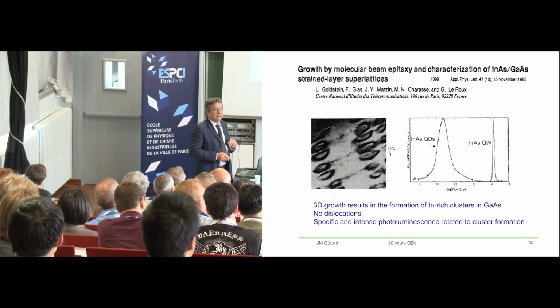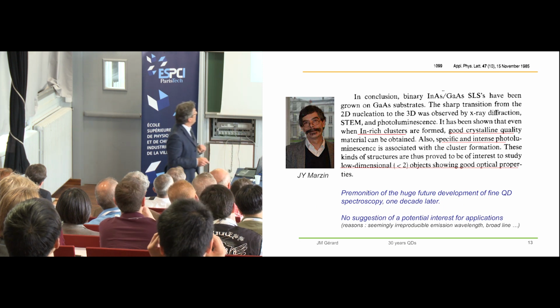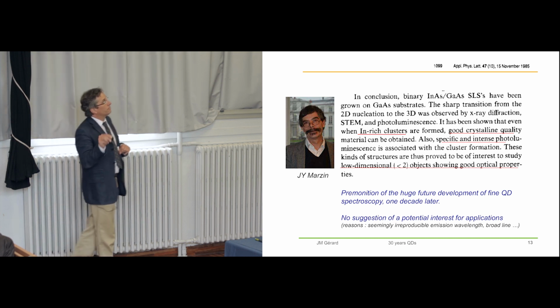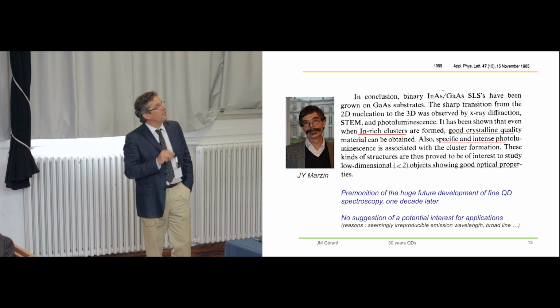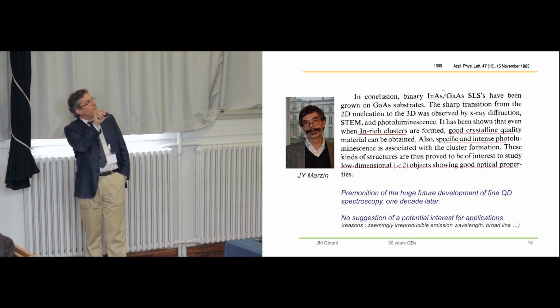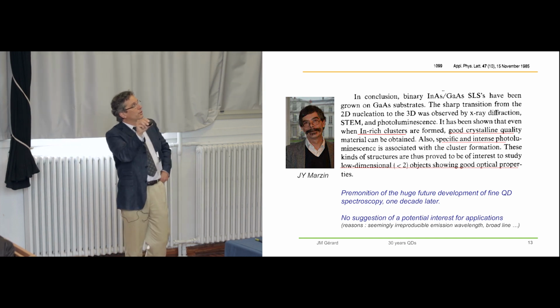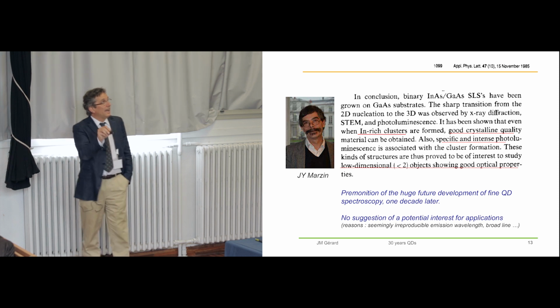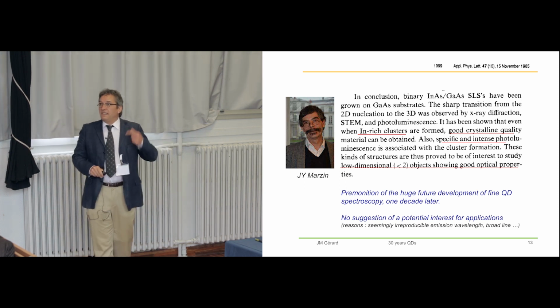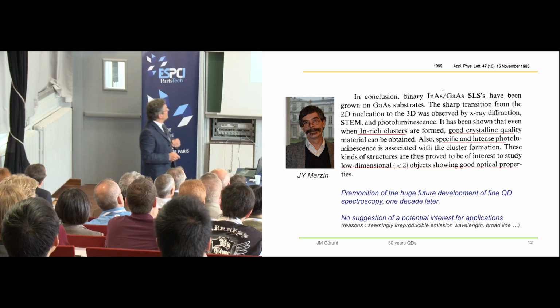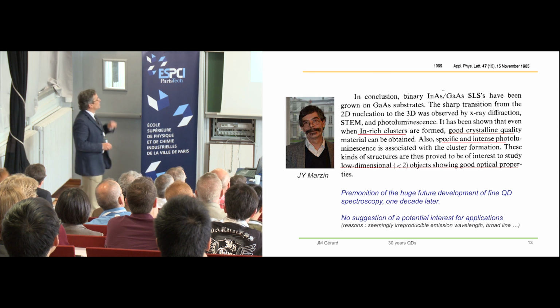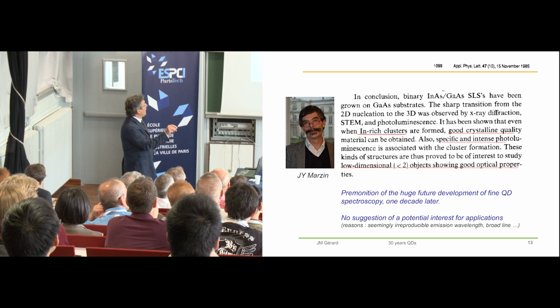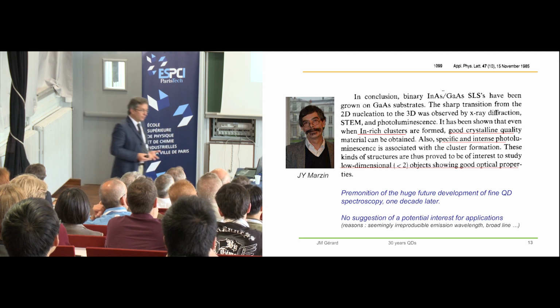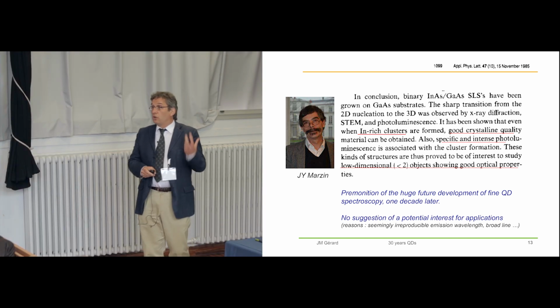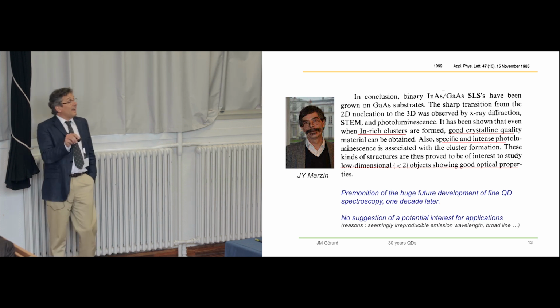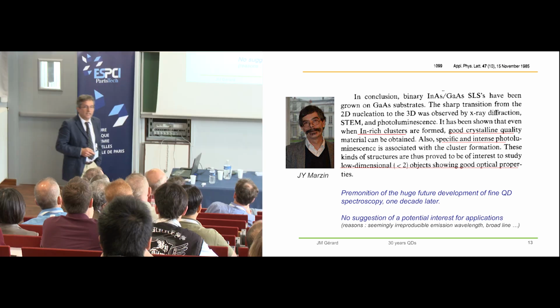So now it's interesting to have a look at the conclusion of this very important paper. The conclusion was, I know, mostly written by Jean-Yves Marzin. And so here you have some comments about the fact that the indium-rich clusters have a good crystalline quality. They have a nice and intense photoluminescence. And you have the last sentence here, which tells you these objects are thus proved to be of interest to study low-dimensional objects with good optical properties. So here you have a premonition of the huge development of fine optical spectroscopy to come on self-assembled quantum dots. At that time, there was no suggestion of a potential interest for applications.